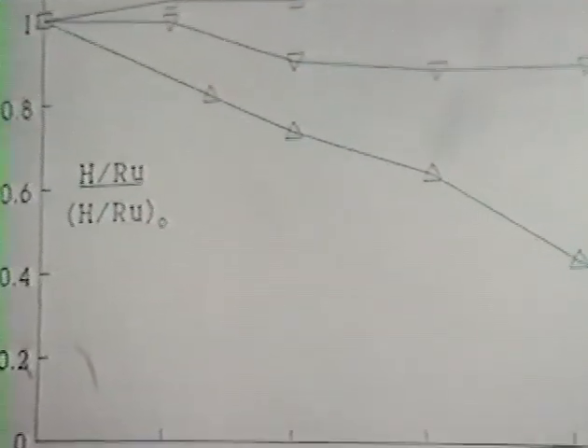This is the rate per total ruthenium in the catalyst. To analyze the system we want turnover frequency, so we need to know the amount of ruthenium at the surface. Hydrogen spills over from ruthenium to copper, so if you try titration using selective hydrogen chemisorption, you get results which are not meaningful. The relative amount of strong hydrogen chemisorption shows essentially no change as you add copper — it's not a good indicator of surface composition.